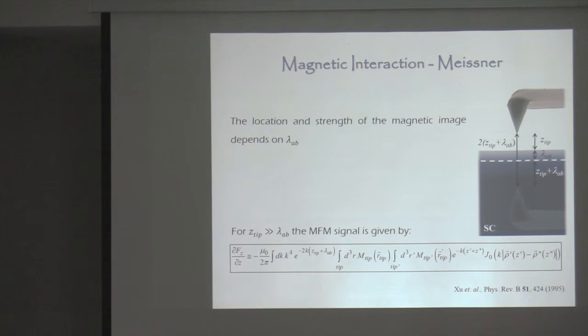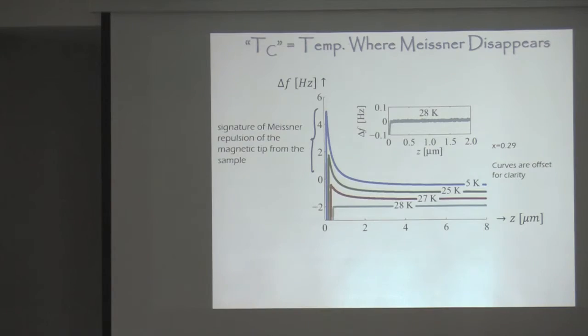So this is what we do, and this penetration depth, as you increase the temperature, is going to become bigger and bigger. So the signal is going to get flatter and flatter. And actually, this allows us to measure Tc locally. Okay. So here you see a sequence of these touchdown curves, at low temperature and increasingly high temperature, and you see that this curve becomes flatter and flatter because the penetration depth is becoming bigger and bigger, and at some point we see a flat signal. This is what you would measure if you would measure a normal metal. And so we can get an estimate from this of Tc itself.